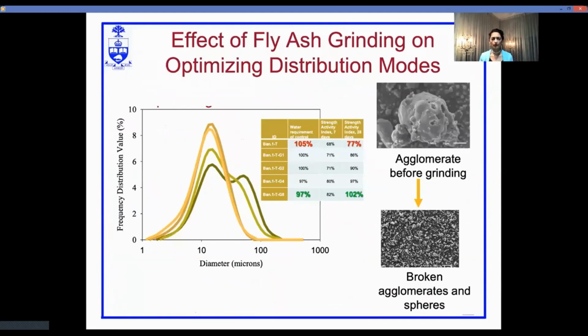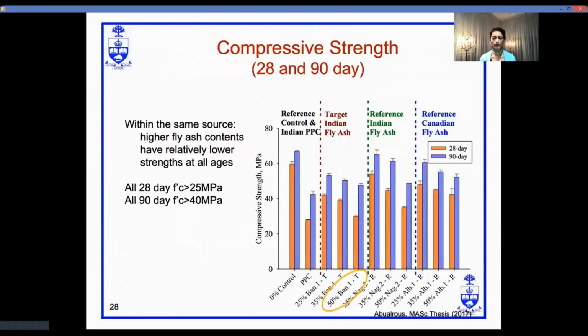So we did various grinding scenarios, and this figure shows the frequency distribution of 4 of those different cases, and we were eventually able to achieve the grinding profile that would meet the physical requirements of the tests in accordance with the Indian standard, American standard, and the Canadian standard.